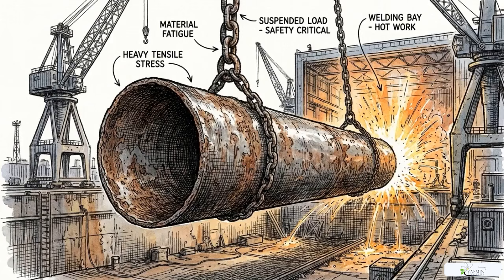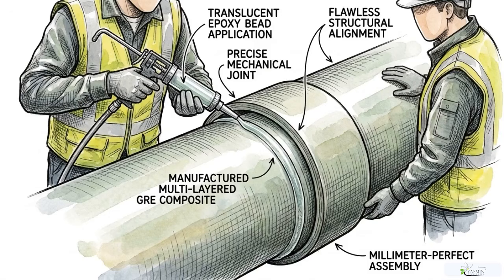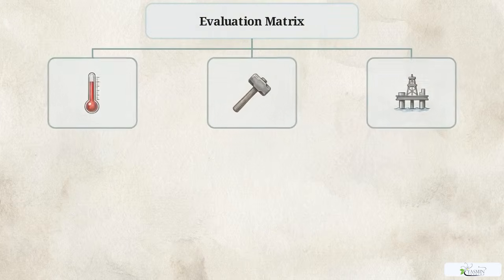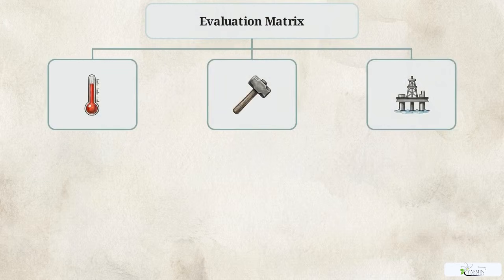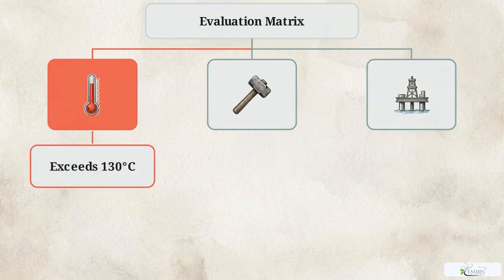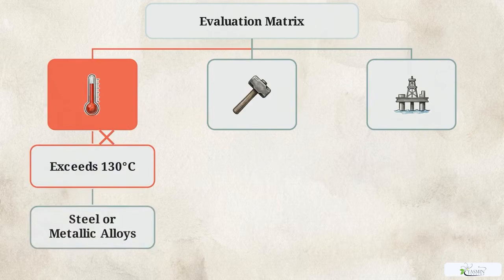We can summarize the operational reality like this. GRE trades the heavy durability of steel for a delicate installation phase that rewards careful teams with decades of performance. To decide if it's right for your project, look at this flowchart mapping out pipeline environments based on temperature, impact risk, and corrosion. If your operations process fluids above 130 degrees Celsius, or if the pipeline will experience continuous mechanical vibration, GRE will fail. You should stick with traditional steel or metallic alloys in those specific zones.